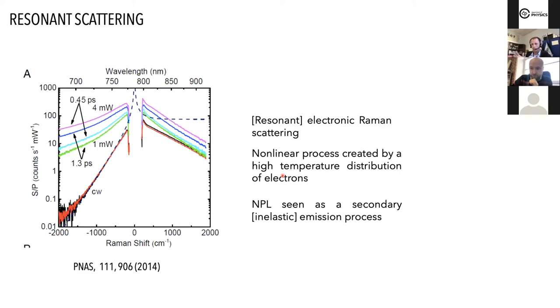So here we're dealing with electrons that are already thermalized between each other to form the Fermi-Dirac distribution. And they are in the process of exchanging energy to the lattice, to the phonons, in this kinetic dynamics decay of the energy. Okay, so the principle here is that we create this high electron temperature, and this nonlinear process is at the origin of this hot electron distribution.